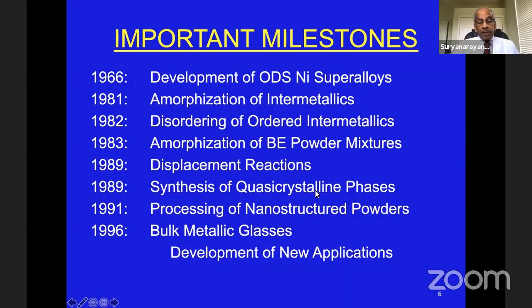And then same year, the quasi-crystalline phases, where the so-called forbidden symmetry, you can have 5-fold symmetry, 7-fold symmetry, 12-fold symmetry, all those so-called forbidden symmetries could be observed in these quasi-crystalline phases. 1991, for the first time, it was shown that mechanical alloying can produce nanostructured powders, powders with nanometer size grains.